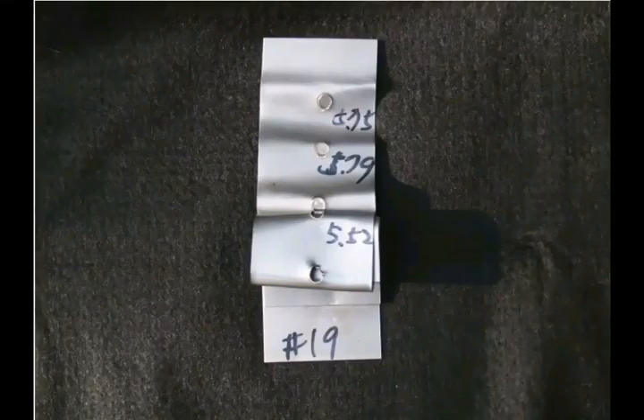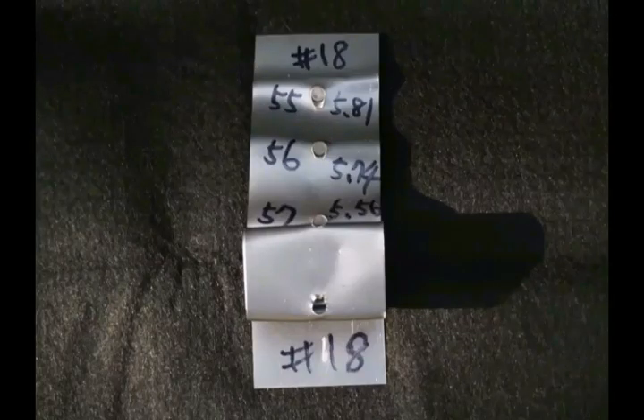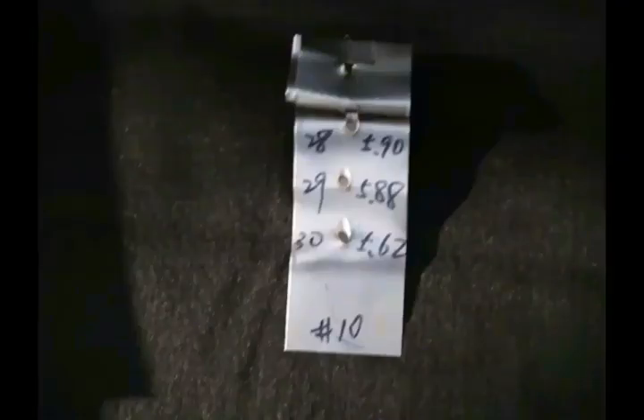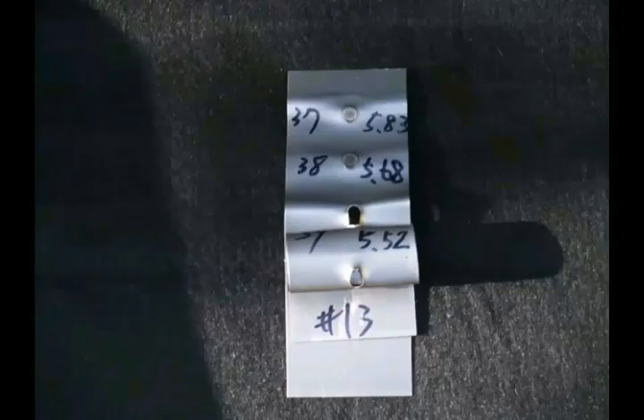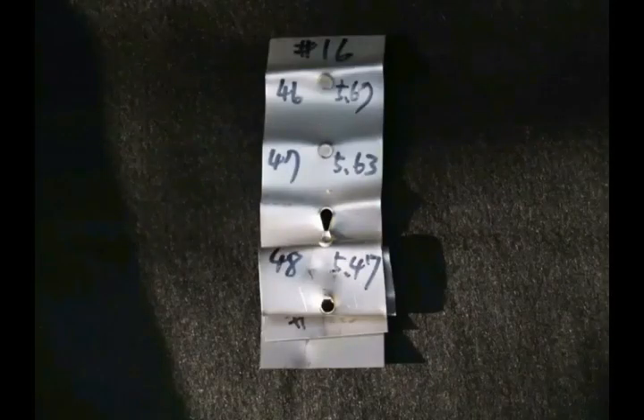These were the peeled coupons I made during 2003 to 2006. They were made without a feedback loop. From the cross-section of my welds, there was no black dendrite at the center. But you can still peel it and get a good quality weld.